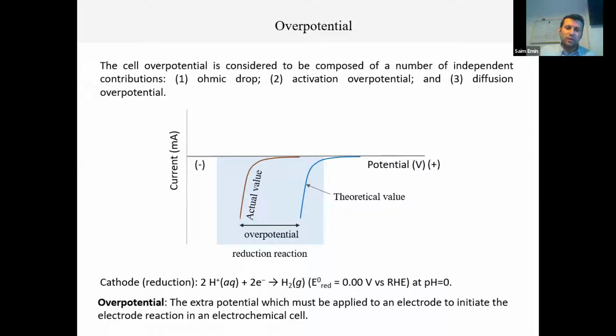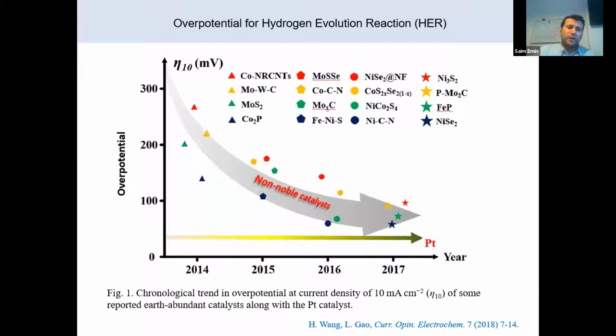Not every material has this kind of catalytic activity for hydrogen evolution. Some are good, some are bad, and this is measured with this current. Sometimes, from this perfect case, which is around 0 volts, we have a shift in the negative direction. This is what we call the overpotential, and we record that value. For different materials, it's different. The overpotential for platinum, which is a very good catalyst, is quite low. It's not perfectly zero, but let's say 30, 40 millivolts, somewhere there.